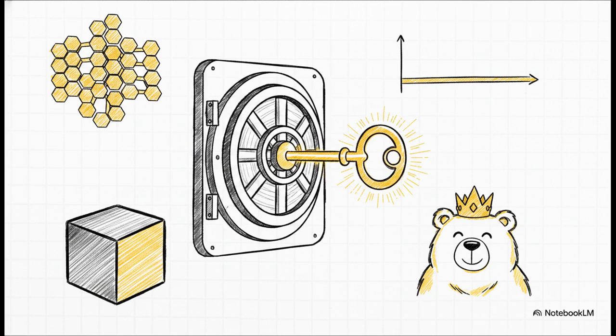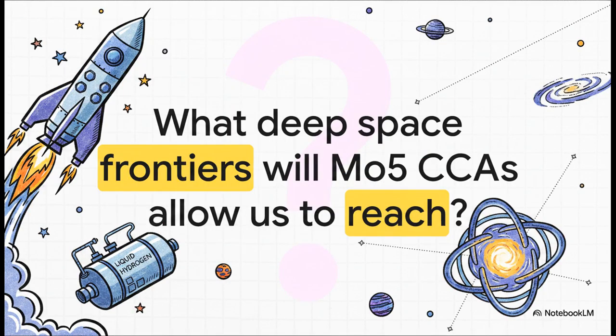First, it produced a noticeably finer cellular structure. In turn, that tighter structure allowed for a significantly higher precipitation of that protective, scaffolding-like mu phase. On top of that, it featured a wonderfully smooth, uniform hardness profile from top to bottom, and of course, it boasted an incredible 7.3 times less internal porosity. Honestly, finding this exact combination of laser speed and power is like finding the cryptographic key to unlocking Mo5 CCA for actual real-world manufacturing. Which leaves us with a totally thrilling prospect.